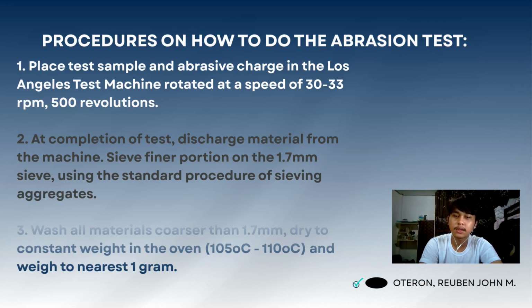First, place the test sample and abrasive charge in the Los Angeles test machine, rotated at a speed of 30 to 33 rounds per minute for a minimum of 500 revolutions. Number two, at completion of the test, discharge the material from the machine and sieve the finer portion on the 1.7 millimeter sieve using the standard procedure of sieving aggregates. And number three, wash all materials coarser than 1.7 millimeters, dry to constant weight in the oven at 105 to 110 degrees Celsius, and weigh to the nearest 1 gram.